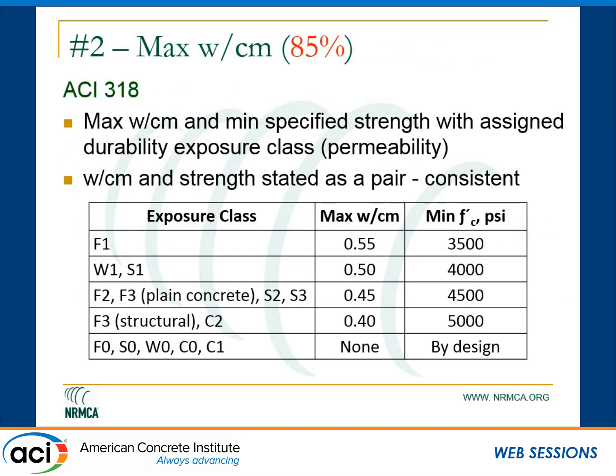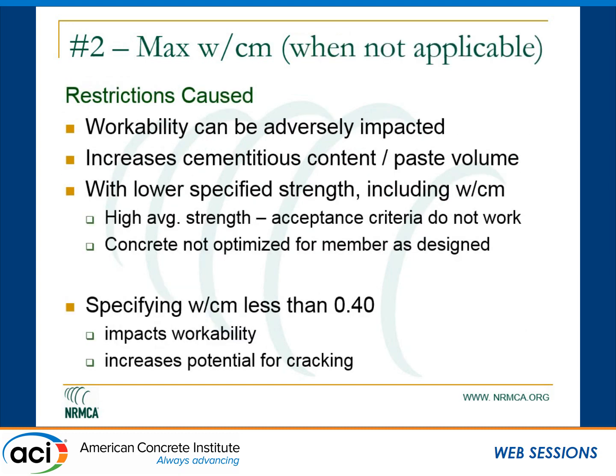When we have a specific exposure class in concrete, as defined by the exposure class definitions in ACI 318 and 301, there are specific reasons when you would use the water cement ratio. So try to stick to the exposure class requirements for water cement ratio definitions.